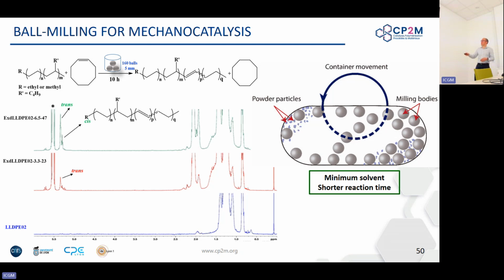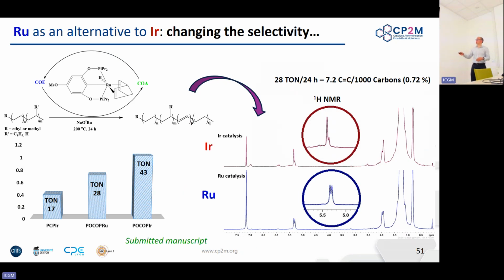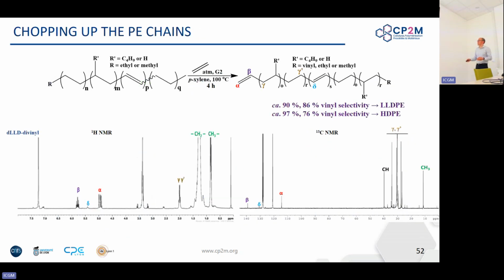And you can introduce a lot of double bonds, a lot of trans double bonds. You can change the metal. You can turn to ruthenium rather than iridium. And this has a lot of advantages because it gives you a little bit more cis product when you turn to ruthenium. This is also characteristic of what ruthenium can do if you want to go cheaper than iridium. And we are trying right now to go even cheaper than ruthenium.